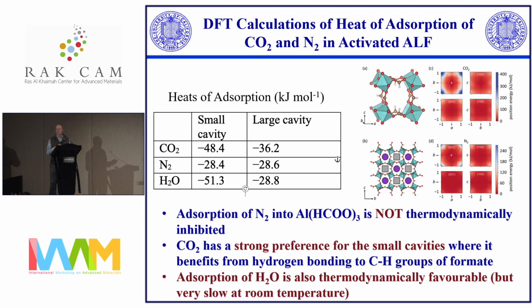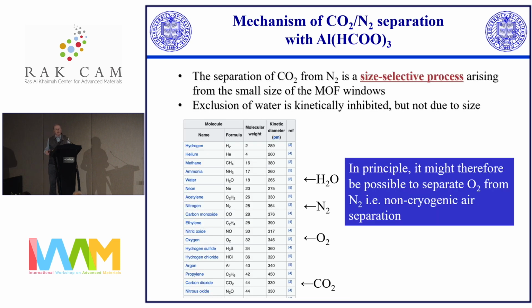So that tells you that there's a kinetic reason, and there's essentially a size effect that prevents the nitrogen from going in. Water's smaller than both CO2 and nitrogen, and so the thermodynamics for putting water into it are very good, but it's kinetically very slow, which turns out to be important. So at least kinetically slow at room temperature. So we got a really good understanding of the energetics of CO2 and nitrogen in the cavities, of the heat maps for the different cavities and so on. So to a first approximation, this is a size selective process where the smaller CO2 molecule, even though it's so minutely smaller than nitrogen, will go into the cavity and the nitrogen won't.